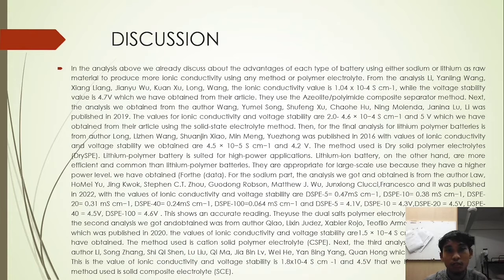Next is the analysis we obtained from the author Wang and his friend, which was published in 2019. The values for ionic conductivity and voltage stability obtained are 2.0 to 4.6 times 10 to the power of negative 4, and the voltage stability is 5 volt. Then the final analysis for lithium polymer battery is from author Long and his friend, which was published in 2016 with values of ionic conductivity 4.5 times 10 to the power of negative 5 and 4.2 volt for voltage stability. The method used is dry solid polymer electrolyte, and lithium polymer battery is suited for high power application.